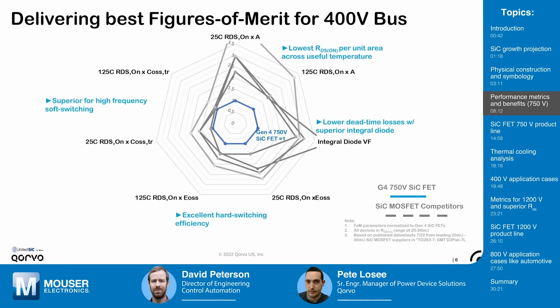The second thing you notice is that if you walk around the radar chart clockwise, you'll quantify or visualize the answer to the question you posed on the previous slide. We start with the lower RDSA, right? And this is true at both 25C and a practical use temperature up to 125C. We talked about the lower forward drop of the integral diode. So this will give you lower dead time losses if your VF is lower, right? And so now we are talking about a VF in a cascode FET of about 1 to 1.5 volts, as opposed to anywhere between 3 to 5 volts with a conventional MOSFET.